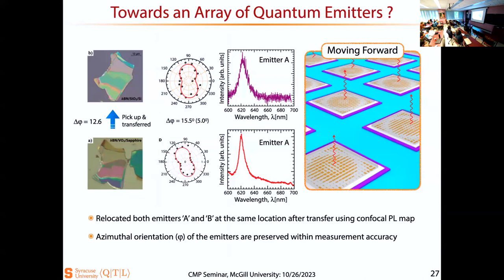Sovik Viswas, who did his internship at McGill when he was an undergraduate at Kharagpur, is working on a dry transfer, and he showed that yes, he picked it up and placed the same emitter on a silicon substrate. You can see that there is a relative orientation change, but with a motorized way of transferring, we were able to make it there. Then we recharacterized the emitter, and by looking at the relative orientation change of the two flakes, we were able to extract that indeed the in-plane dipole moment didn't change at all. The quality of the emitter didn't die off.